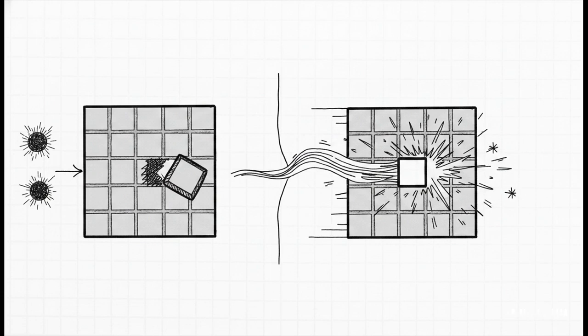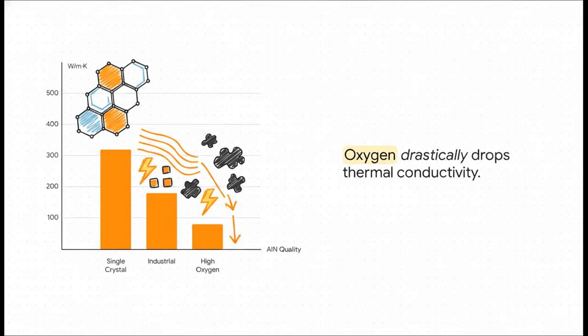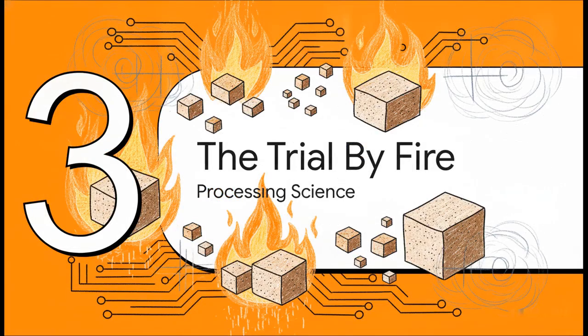They just crash. You can really see the real-world consequences of those oxygen potholes right here. A pure single crystal sits at that theoretical 320 watts per meter Kelvin. A really good industrial ceramic hits about 180, which, by the way, is still fantastic for electronics. But if you have high oxygen contamination in your starting powder, your thermal conductivity completely plummets to 80 or sometimes even lower. Literally, just a tiny bit of oxygen ruins the exact reason we're using this expensive material in the first place. So how do we fight back?